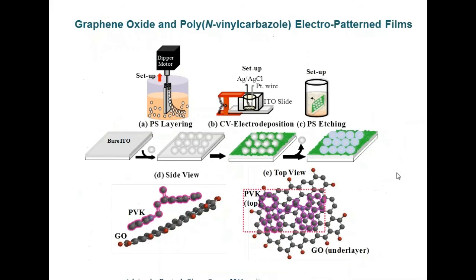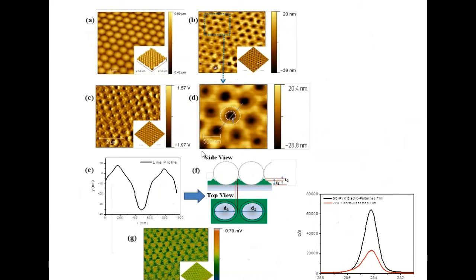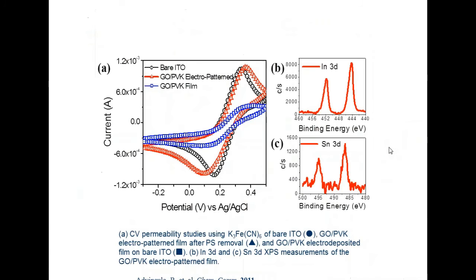And we were successful, for example, in utilizing the same material in a patterning scheme that you're now familiar with, and that we can deposit the graphene oxide together with the PVK in patterns like this, where we've demonstrated useful applications such as transport properties of membranes and ion-gated channels that may be mimicking that of nanovalves. And here is the molecular ion probe experiment as well as the XPS measurements that allowed us to distinguish the presence of holes or pores on the surface of the film.